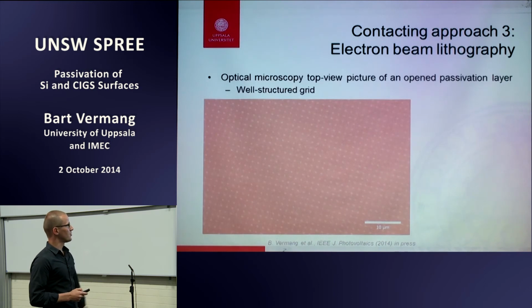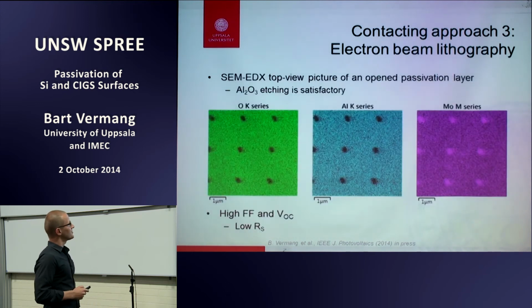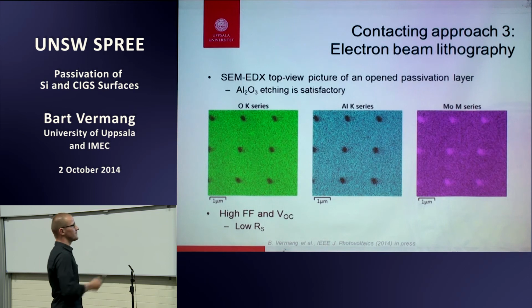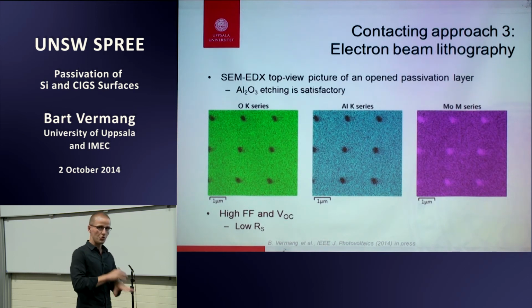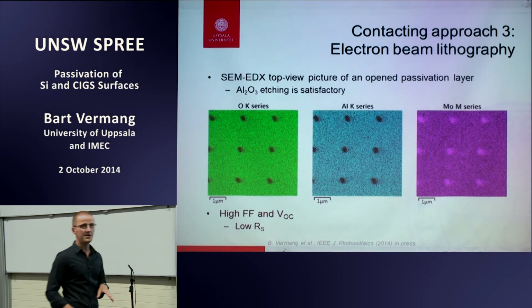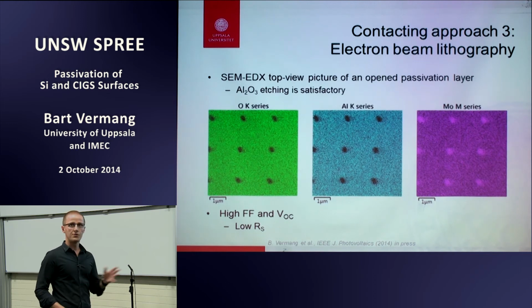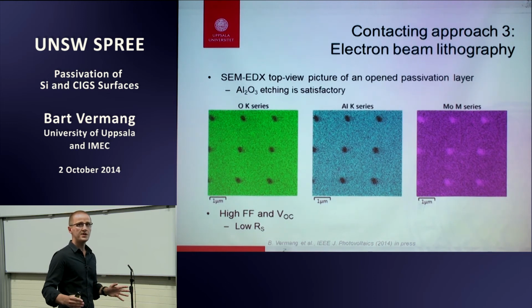Like here, for example, an optical microscopy picture. Top view, these are openings of around 200 nanometers, which you can still see in optical microscopy pictures. A bit closer, again, SEM EDX, where you can see that the openings are quite nicely opened. And the advantage of this approach is that you control the grid very well. So you can say, I want 1.5 micrometers or 500 nanometers in between the nano-sized openings, and the openings themselves have to be this size. So you can really optimize things.